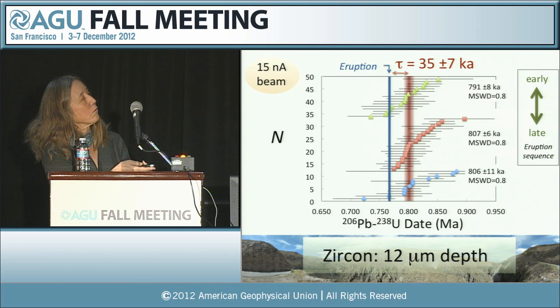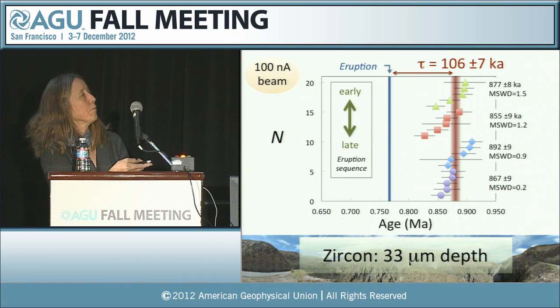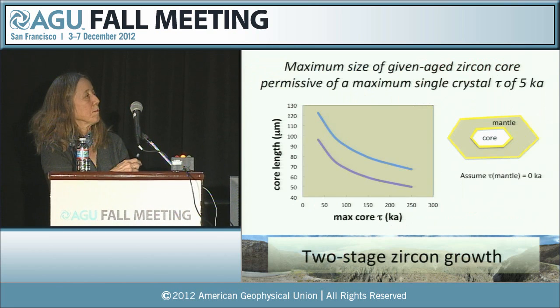Since you can see this now, again, let me quickly explain this. This is just showing you that these are organized in sequence from early to late within the eruptive sequence, but within each rock, I've organized them in terms of just increasing ages. And you can see there's no real evidence of a distinctive age progression as you go up through the stratigraphy. 12 microns, 35,000 years before eruption. 33 microns, 106,000 years before eruption. And you've all had a chance to look at the data. And so with the 100 nanoamp beam, we do actually get more precise ages, except on the rims, and the rims just don't seem to want to cooperate.